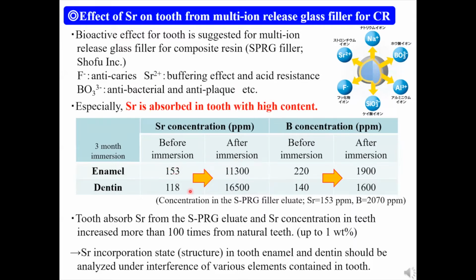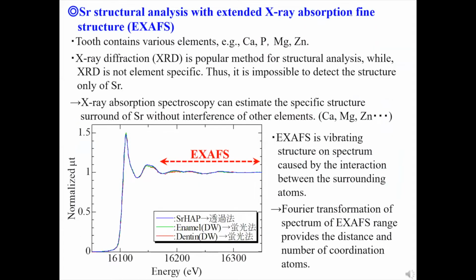The initial content of strontium in tooth enamel and dentin was roughly 100 ppm, but after immersion in a strontium-containing solution, the concentration drastically increased up to 10,000 ppm. We tried to estimate how the strontium was absorbed into tooth enamel and dentin. For this purpose, we applied another X-ray absorption spectroscopy, called EXAFS, Extended X-ray Absorption Fine Structure.